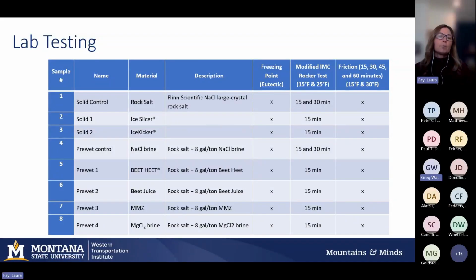So we took all the information from the literature review and the survey, and we came up with a list of potential rock salt and additive blends. And we proposed some test methods. And what we landed on was basically what's shown in this matrix for a testing plan. So we landed on 8 different products to be tested. And those were a solid rock salt and a clean one. So we used a lab grade purchased rock salt, a mined rock salt, Ice Slicer, and then another commercially available rock salt with an additive, which is Ice Kicker.